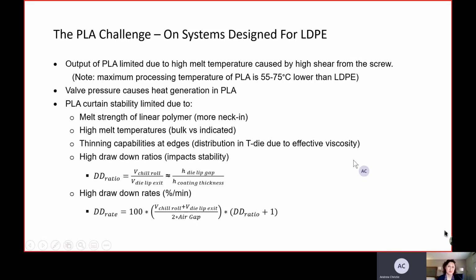The challenge for PLA, because of the different polymer structure of PLA and the thermal sensitivity of the polymer, we are limited in the temperature that we want to process this at. Typically, that is going to be 55 to 75 degrees Celsius lower than the objective temperature for low density polyethylene. So when we put the PLA into this high shear screw for polyethylene, it's going to overheat before we get to a reasonable output.